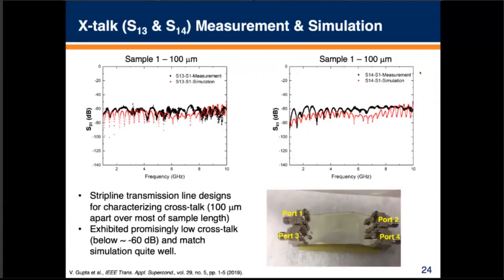Another really important aspect of the transmission lines, especially when you're dealing with a densely integrated system, is crosstalk. So how does one trace talk to another trace in these structures? The test structure we use for that is shown here, and it has a top ground, so you can't see the actual traces, but they come off along this way, and over a significant portion of the length of the sample, they're in close proximity together. They're approximately 100 microns apart, so they're very dense in this structure, and would be closely coupled if there was significant crosstalk.